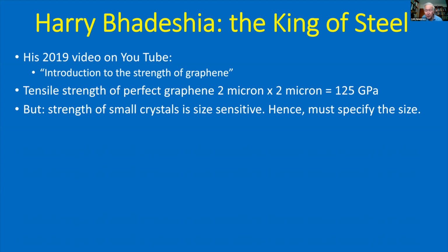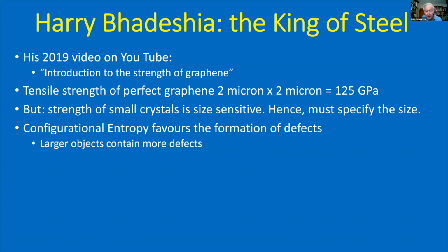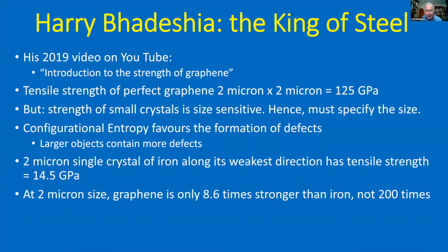And so he says, quite rightly, of course, you shouldn't talk about strength without specifying the size of these small crystals. And as we know, configurational entropy favors the formation of defects. So all macroscopic materials contain many defects, and large objects contain more defects than small objects, of course. So Harry says a 2 micron single crystal of iron along its weakest direction has a tensile strength of 14.5 gigapascals. So if you compare a 2 micron piece of graphene with iron, the graphene is only 8.6 times stronger than iron and not 200 times. So this statement is just incorrect.